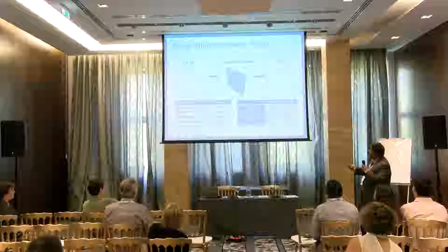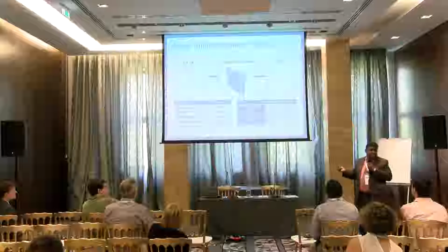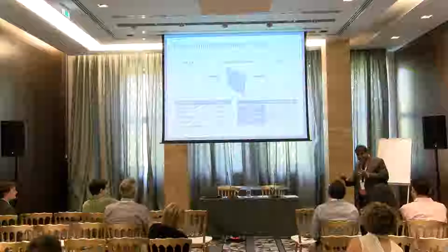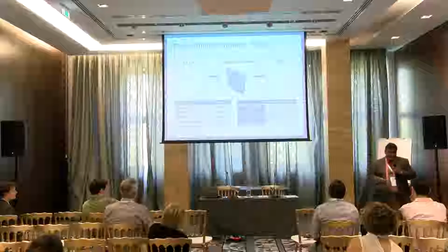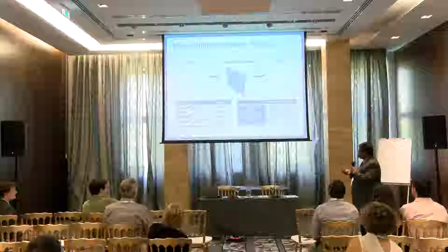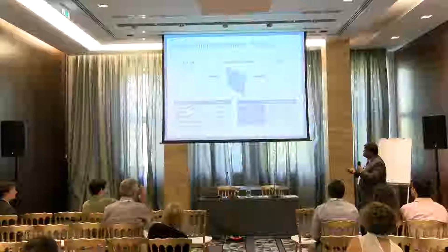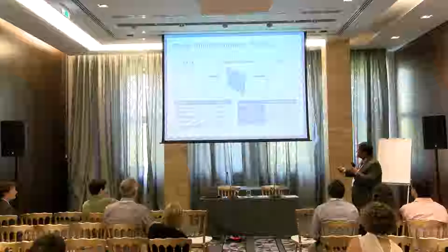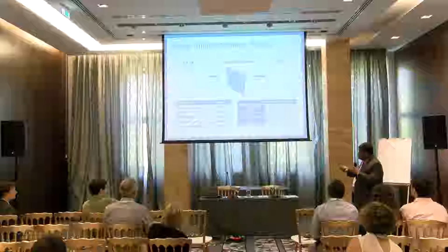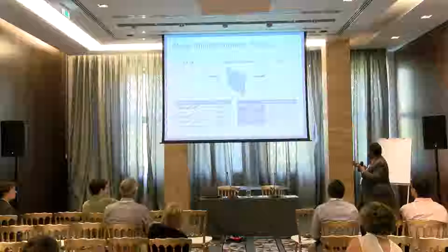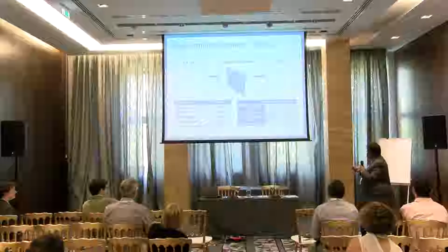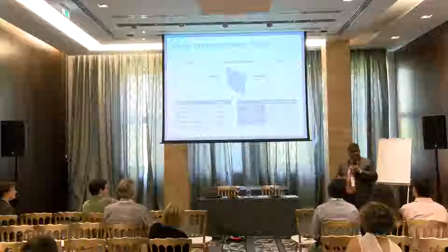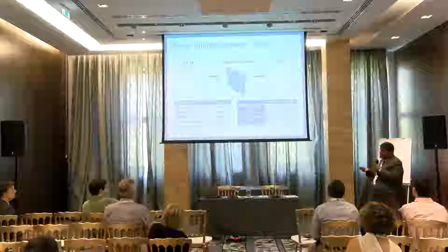If you mesh these unit cells with 1D elements, which is equivalent to a truss element or a spring mass element, it doesn't even take into account bending, which normally happens in a hard impact phenomenon. So these are the dimensions. Our cross-section was 0.04564. Weave friction was 0.19. We had about 4,500 unit cells, which is what the results I'm showing here are based on. And these are the properties for the warp yarns and fill yarns: Young's modulus, Poisson's ratio, ultimate strength, and thickness, which we actually measured from the fabric we had. So we have used typical values for this experiment.